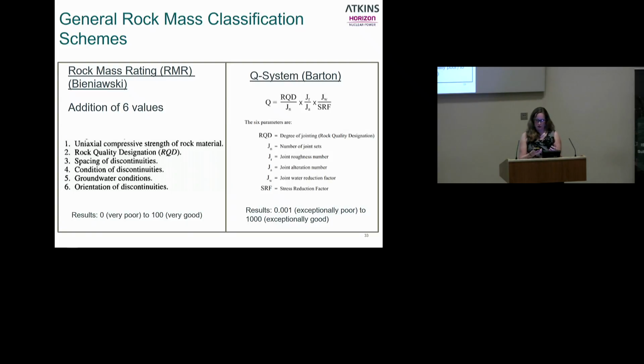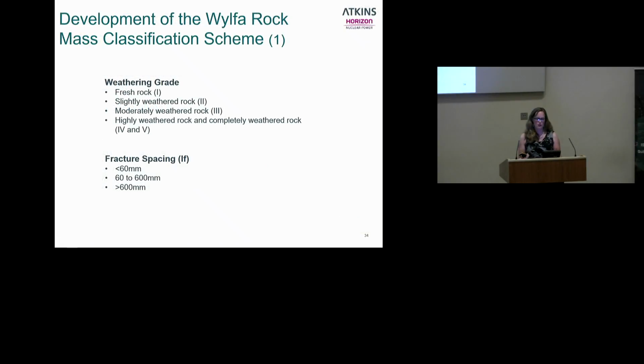So we decided to modify these and sort of come up with our own site-specific rock mass classification to give an idea of where the poor and the good quality rock was. We went through various options, but we came up with using just 2 input parameters: fracture spacing and weathering grade. Fracture spacing, similar-ish to RQD, but it just gives that extra level of detail where RQD can actually miss some of the spacings that are given. It's not really fine enough detail. And the weathering grade, this is sort of for the rock mass and not just the discontinuities.